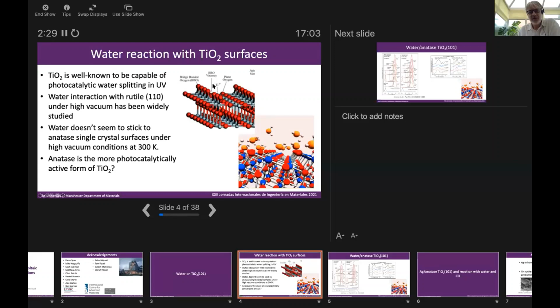And it's fairly well accepted now that if you adsorb water onto this surface, the water will physisorb to the surface. It will kind of skate along the surface until it finds a vacancy in these so-called bridging oxygen rows. So this is the structure of the titanium dioxide 110 surface. We have the oxygen vacancy here. When the water reaches this oxygen vacancy, it will hop into here and dissociate so that a proton, a hydrogen ion, will jump onto a neighboring bridging oxygen, and then we'll have two hydroxide species on this surface.